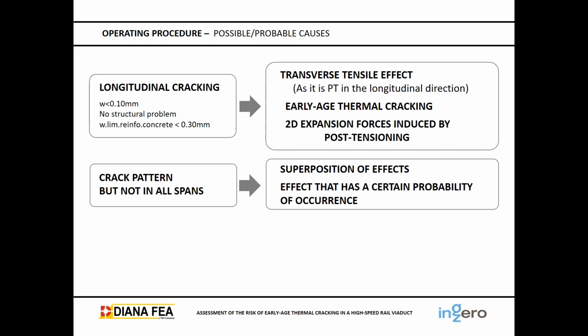Okay, so, the possible or mostly probable causes. This is longitudinal cracking. As I have said, it's very small, less than 0.10 millimeters. It is not a structural problem because the limit for the transverse direction, for reinforced concrete in the Spanish standard, is 0.3 millimeters. And as the direction is longitudinal, it should be due to a transverse tensile effect. So it could be early age thermal cracking or 2D expansion forces induced by the post-tensioning. As I said, this is a crack pattern, but not in all spans, so it leads us to say that it could be a superposition of effects, an effect that has a certain probability of occurrence. So sometimes it happens, sometimes not.